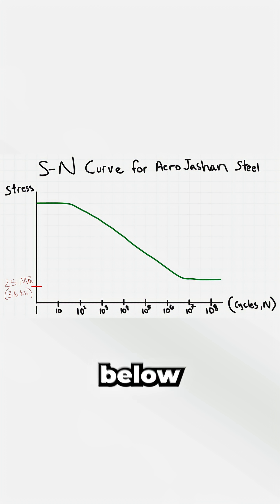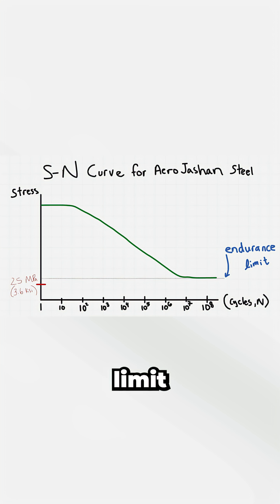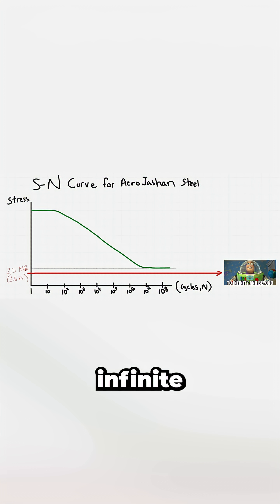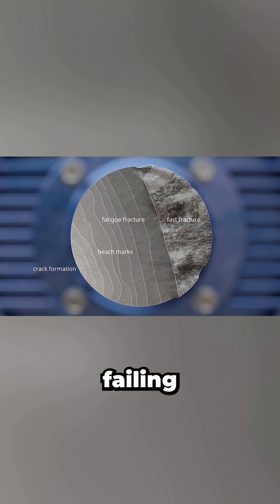But if the stress range is low enough, below a threshold known as the endurance limit, the S-N curve flattens out. That means the part can theoretically survive an infinite number of cycles without failing from fatigue.